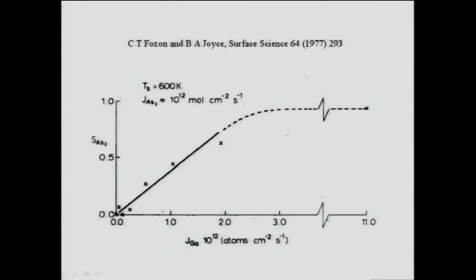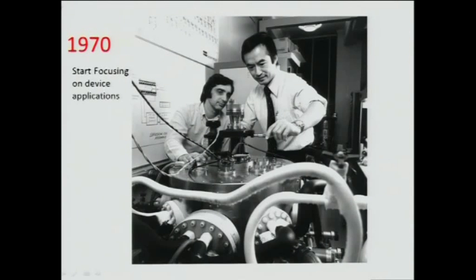Later on, at Redhill, Philips, in England, Tom Foxon and Bruce Joyce in 1977 also repeated the experiment, studying the sticking coefficient of arsenic as a function of the gallium beam arriving on the surface. Notice here, he also found that as the gallium atom flux on the surface increased, the arsenic sticking coefficient also increased, reaching a plateau at a 1-to-1 ratio. So this is how MBE started, with this surface physics study, the surface kinetic studies of atoms bouncing on gallium arsenide surfaces.